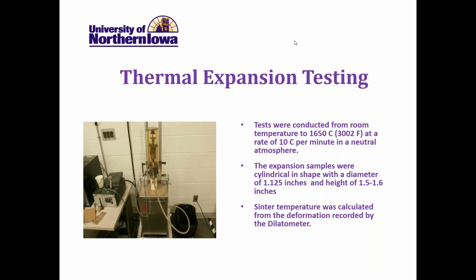One of the first tests that we perform on materials for looking at the applicability in molding processes is high temperature thermal expansion testing. We want to make sure that, one, we're not seeing drastic changes in the morphology of the material or thermal breakdown due to high temperatures. We'll run our tests up to 1650 degrees C, which is much higher than normal pouring temperatures for iron castings. And as we increase the temperature, we put a small amount of force on that sample. And what that allows us to do is see very accurately where the sinter point of those materials are.